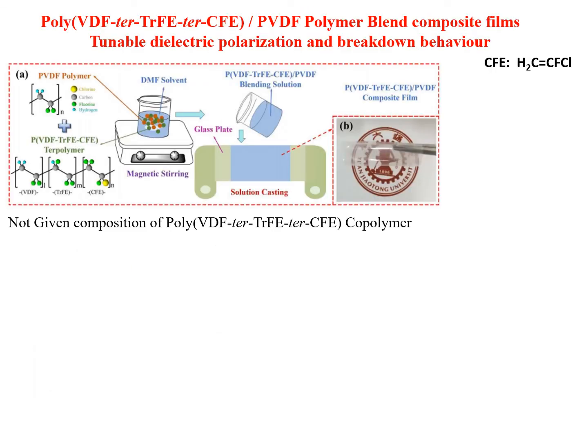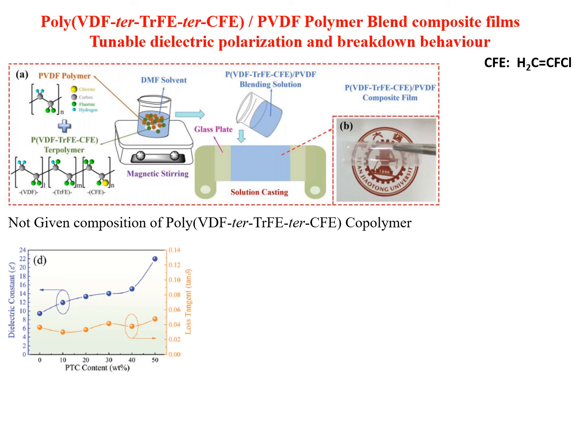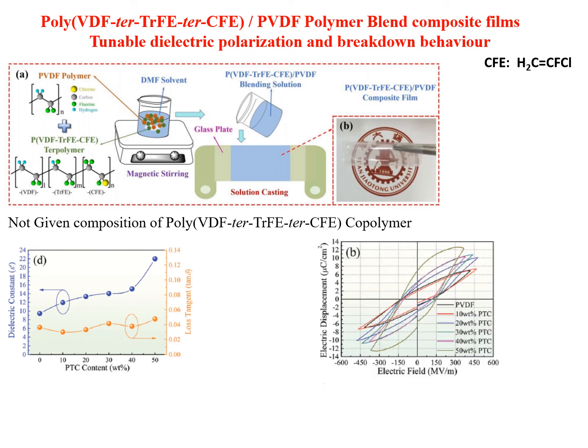And finally, the last one is a blend of a terpolymer based on VDF, trifluoroethylene, and chlorofluoroethylene. This is another terpolymer sold by Arkema, making a blend in PVDF at about 180 degrees in an oven and then quenching. They observe that the dielectric constant is rather high when you increase the terpolymer, even at 40%, while the loss tangent is not so critical. The DE loop shows that again with PVDF you have this piezo-ferro behavior, and it's getting slimmer and slimmer as you increase the content of the terpolymer.